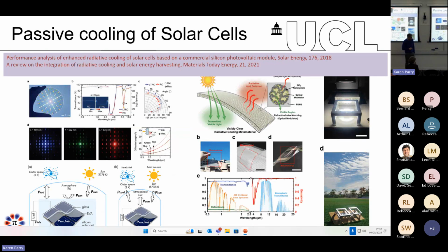Another application of very special importance is how to improve the efficiency of solar cells. And of course, we know that when a solar cell is being heated up, and in the summer, sometimes solar cells operate at a temperature in excess of 50, even 60 degrees. For every degree above 25 degrees, the efficiency of a crystalline silicon solar cell reduces by between 0.3 to 0.5%. So you can imagine that if you go up to 60 degrees, then you have a 15% loss in solar cell efficiency. So people have come up with a lot of designs in order to integrate radiative cooling with solar cells to reduce their temperature. Of course, the challenge here is that you should allow the majority of the solar radiation through in order for the solar cell to operate.